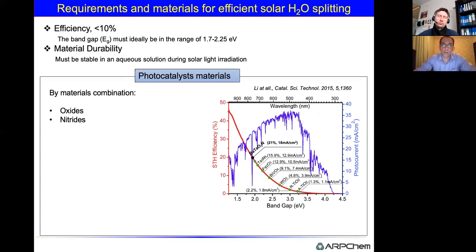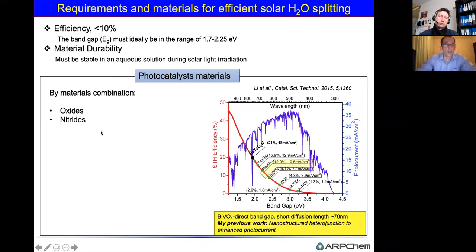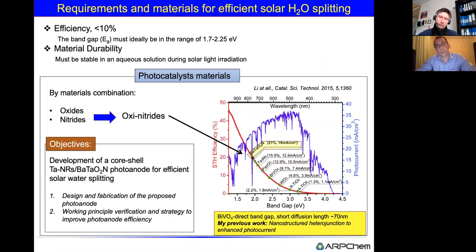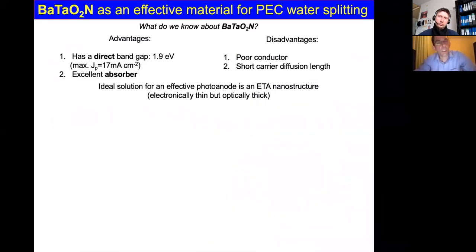Okay, so this material is called barium tantalum oxynitride, because its band gap is much lower. It's 1.9 electron volt. Thus it can generate around 18 milliamp per centimeter square of photocurrent, and the theoretical solar to hydrogen conversion efficiency can be 21%. So it's about 6% higher in comparison to the Ta3N5. Okay, by the combination of the oxide and nitrides, we can actually develop another efficient photoanode material. So now let's look at what we know about the barium tantalum oxynitride material.